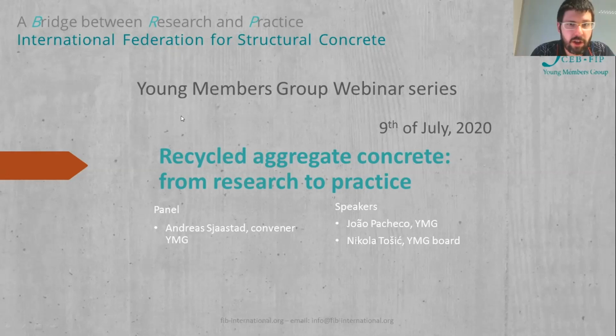Thank you. What about the addition of fly ash in the mixes consisting of recycled aggregate concrete? Yes, we had studies of these, and the effect of fly ash will remain: slower hydration, slower compressive strength gain. You're going to see a linear superposition of the effects. So it's not going to be something where the effect of the two is above the separate effects of one and the other.